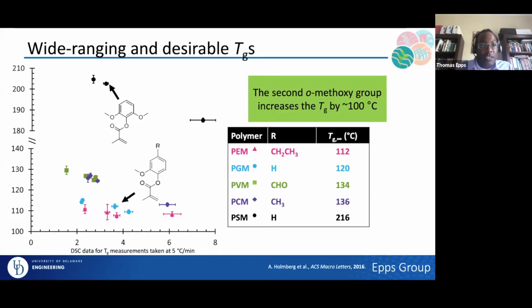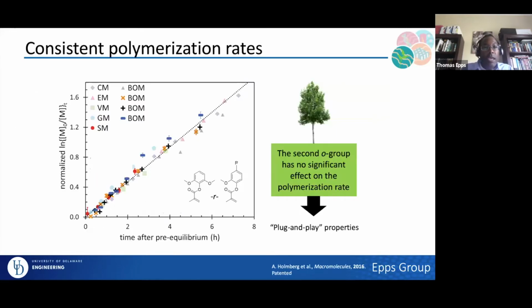And so that's quite nice for two reasons. One of them is that you can imagine that I can co-polymerize these different types of monomers because I have methacrylate functionalities on both. But the second thing is that I can actually start making polymers with glass transition temperatures above 200 degrees from material that I would otherwise burn or throw away in a landfill. And so what can we do with this?